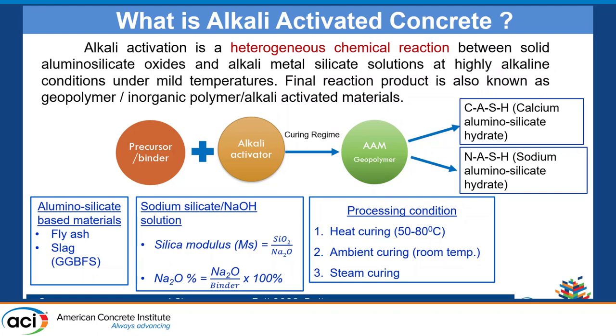These two reactants are reacted following a specific curing regime. Researchers have used heat curing, ambient curing, and steam curing. After this alkali-activation process, the product is called an alkali-activated material, geopolymer, or inorganic polymer. It mainly consists of two major chemical compounds: calcium aluminosilicate hydrate (C-A-S-H) and sodium aluminosilicate hydrate (N-A-S-H), or a combination of both.